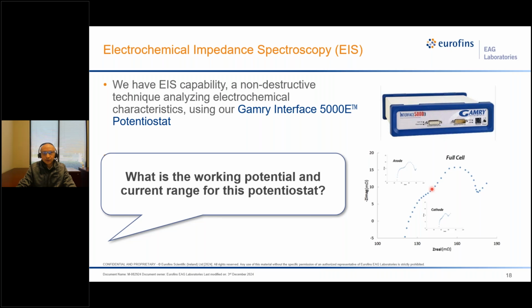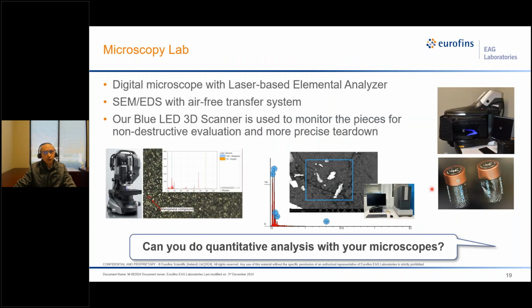And after this, we also have a microscope room within our new battery lab. So far we have 3 microscopes. The first one is the Keyence digital microscope equipped with a laser-based elemental analyzer. Also, we have a SEM with EDS function. It's a benchtop SEM. It's very small, but it's very convenient. This SEM is also equipped with an air-free transfer system, which means we can directly transfer the sample from the glove box to this SEM without exposing it to any air, oxygen, or moisture.